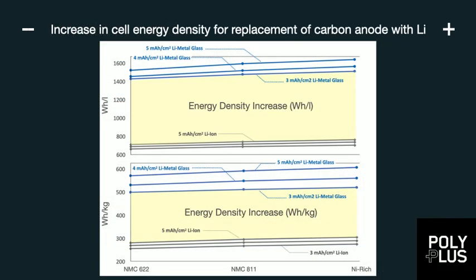And here you see the increase in energy density in yellow as you move from carbon to lithium metal, and it's quite significant. So you're looking at watt-hour per liter values upwards of 1400 watt-hours per liter, and on the gravimetric side over 500 watt-hours per kilogram if we go fully solid state. So that's significant, and of course a lot of that is due to the replacement of carbon by lithium, but there are other things that are involved in here as well.